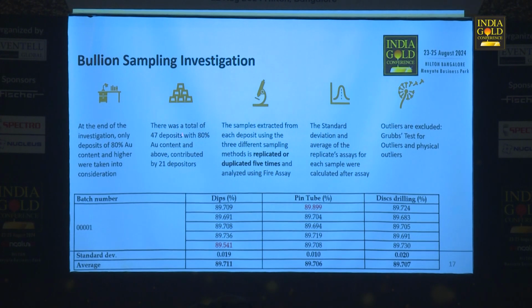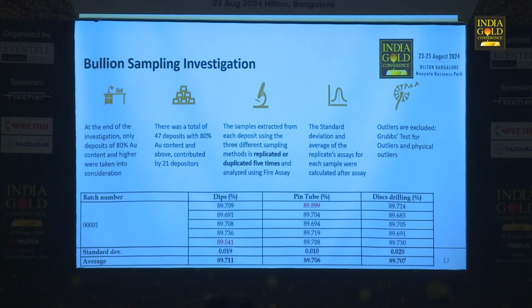That led us to have 47 deposits that are 80% and above, from 21 depositing customers. Those are mine doré. Each result was repeated 5 times on the 3 techniques, and then we looked at the standard deviation. For the outliers, we eliminated them using the Grubbs test. So this is an example of how we did it: the ones marked in red were outliers and were eliminated. Then we looked at the standard deviation and the average.